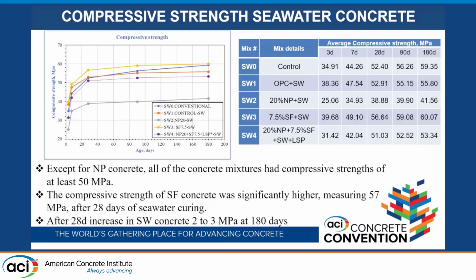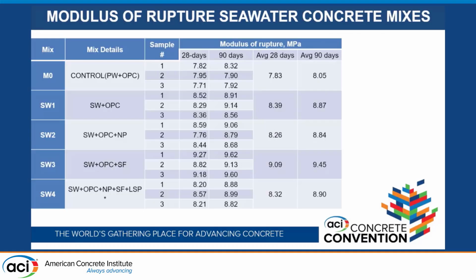By the way, I forgot to mention that all of them were made of seawater and cured in seawater, collected from the same source. After 28 days, the increase in the seawater concrete was 2 to 3 megapascal at 180 days. So there's no significant increase beyond 90 days in the compressive strength.